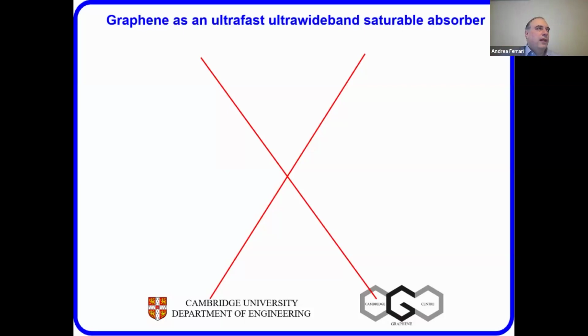But also, if you look at the Dirac cone, it immediately tells you that the material is ideal for optoelectronics, because if you arrive with a laser of a certain wavelength, you can always excite an electron-hole pair, no matter what wavelength you're using. And that's quite unique. If you take another material, it usually has a band gap, or even a dot with subbands, you will only be in resonance with one of the subbands for a given wavelength. Here it is like having an infinite number of subbands.